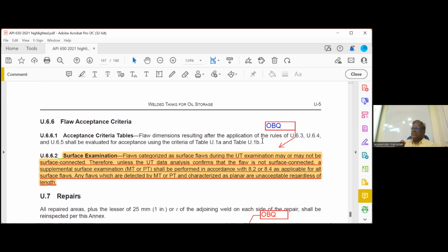So what the code says is, by UT, if you are marking some defect on the surface, it should be confirmed with MT or PT. But if MT or PT says it is a linear defect, linear meaning like crack or lack of fusion, repair is mandatory. Don't worry about the ultrasonic results. Okay, so this is important.